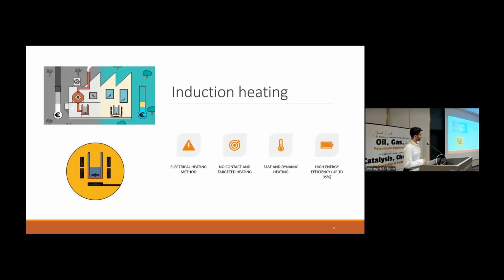So for example, if in our core we put two types of material, one which is magnetic and the other non-magnetic, we're going to only be heating our magnetic material. And it's fast and dynamic heating, so we can have really fast heating of hundreds of degrees per second. And it's dynamic because, for example, if you want to control the temperature, we can control it really precisely. And also, once we stop the magnetic waves, our heating will stop also directly. And lastly, it's really high in energy efficiency. We can get induction processes with energy efficiencies up to 95%.